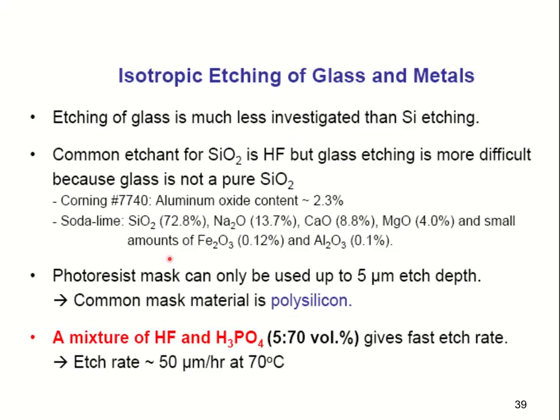Also, as a masking material, photoresist can only be used up to 5 micron etch depths. So that means if you need more than 5 micron etching, then polysilicon is recommended rather than the photoresist. For a fast etch rate, you can mix HF and H3PO4 with this volume percentage, and then at 70 degrees C, the etch rate is 50 micron per hour. So this is quite fast.